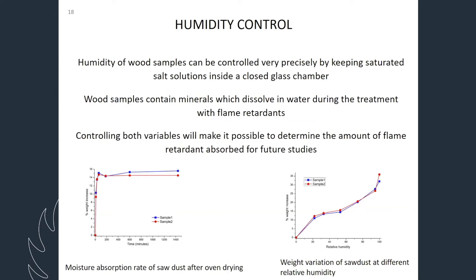Later we realized that all wood samples have some soluble salt or soluble minerals. When we put them in solution, then part of it dissolves in water. And that also we measured, how much we can lose. So in the future, we can use all these variables to understand exactly what is the weight of the actual wood in our sample. So we can quantify the amount of flame retardant in the sample.